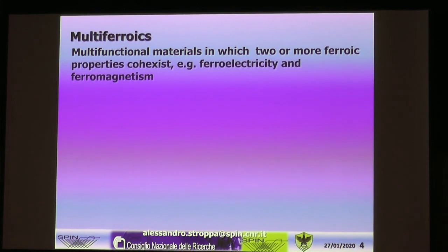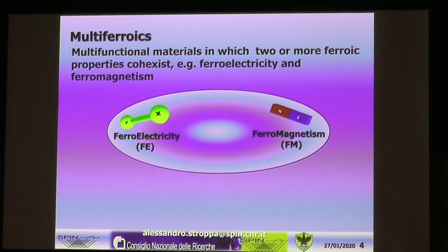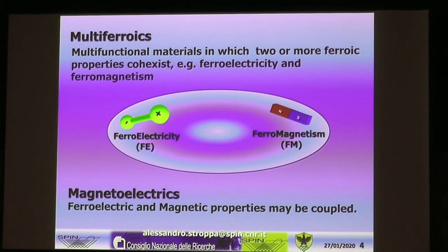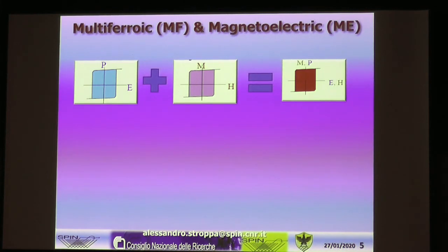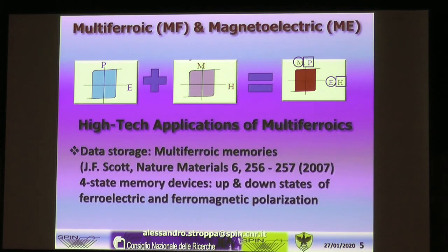We are considering multi-ferroics — materials which show the coexistence of ferroelectricity and magnetism in a single-phase compound. With this coexistence and the coupling of the two orderings, we get magneto-electric properties. Using these materials, we can change the magnetic polarization with an external electric field, or play with the ferroelectric polarization using an external magnetic field. This enables memory elements with four states: up/down electric polarization and up/down magnetic polarization.